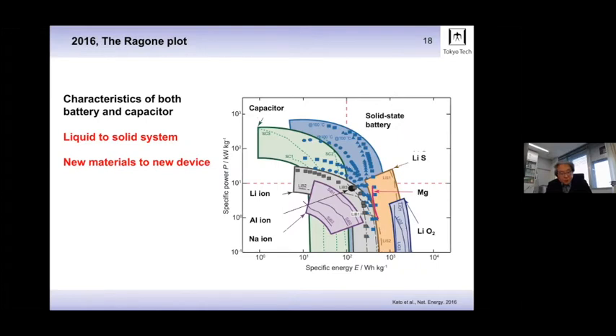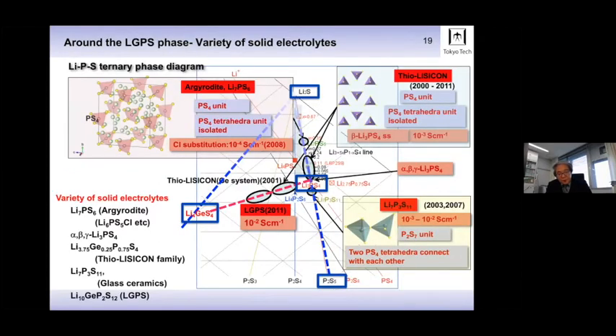So again, the Ragone plot. As already mentioned, it is clear that the most unique feature of the solid state is their power characteristics. The sulfide electrolyte works quite well in all-solid-state batteries. So there are many candidates for the sulfide-type solid electrolyte. This figure summarizes these many types of solid electrolyte: thio-LISICON, Li7P3S11 materials, so-called glass ceramics, argyrodite, and LGPS. In the very narrow region of the ternary or quaternary diagram, many different types of crystal structure exist, and most of these structures show very high ion conductivity.